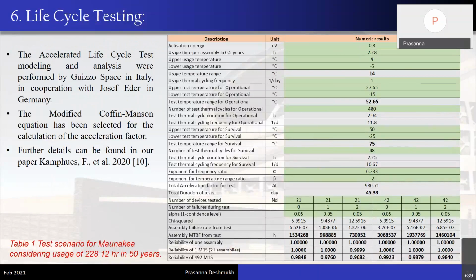So as I said before, in order to estimate whether our warping harness mechanism is reliable or not, and whether it meets those failure requirements, so one failure per year kind of requirements, we have to do accelerated life cycle testing, for which we took help from Guizzo Space in Italy, as well as they collaborated with Josef Eder, which is another company in Germany, and they did calculations for us for estimating how many actuators can fail if we take a set of say 21 warping harnesses, which is a representation of a single SSA module, or 42 warping harness mechanisms. And in this, how many actuators can fail during this life cycle testing, so as to predict what will be the failure rate during the operation, when you have 10,000 plus warping harness mechanisms, and when you have realistic temperature conditions.